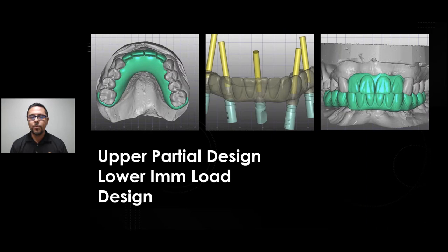In this case I asked for a stone model because I knew I needed the stay plate. When we post-process a stay plate, you want to make sure you throw it in the Otoflash on the model, because it tends to warp. The most retentive part is those little C-clasps designed onto the distal end of those molars. If this print warps in any way, you're not going to get the warpage back to the original fit. So you place it onto the model and run it in the Otoflash a couple of times. Once it's gotten its first cure, you can take it off and it won't warp — it's pretty much well set.